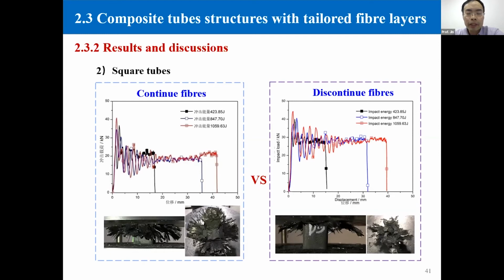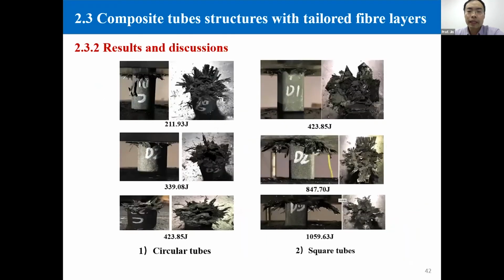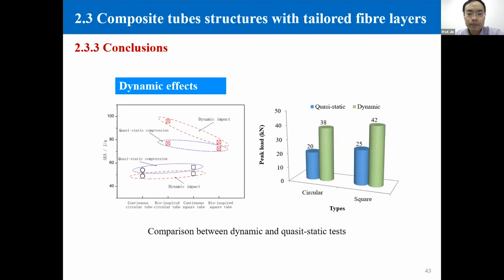And we compared both the circular tubes and the square tubes. And this is the failure mode of those structures. And we can see that the composite tube is crushed to small debris. That means it absorbed more energy. And finally, we summarize the energy absorption. We notice that for the normal tube, the energy absorption at constant rate is higher than the energy absorption at a dynamic loading rate. But the composite tube with discontinuous fiber can achieve a higher energy absorption at a dynamic loading rate.